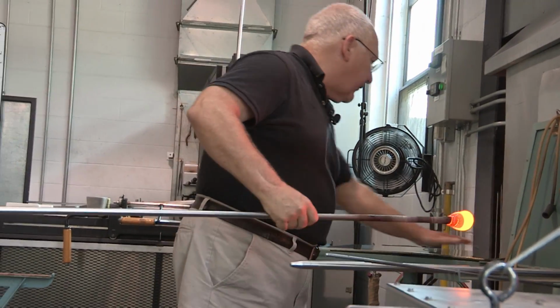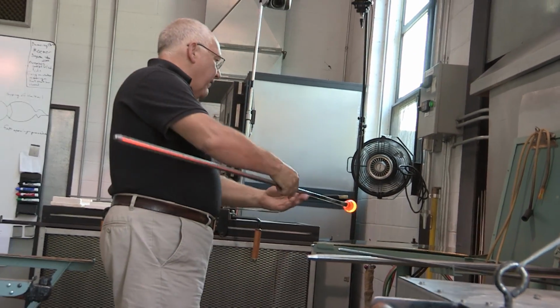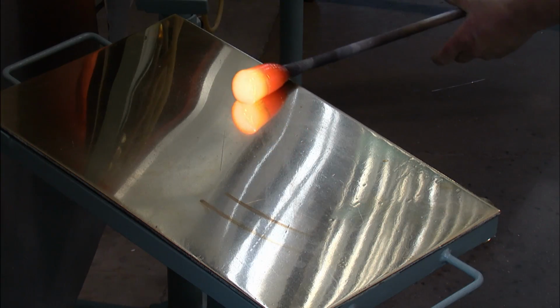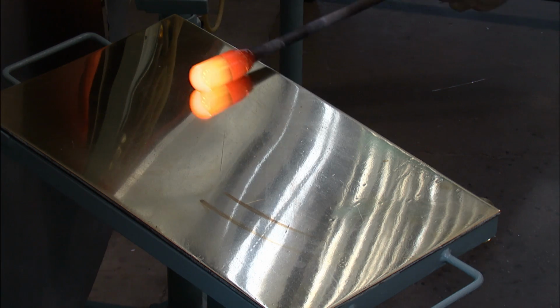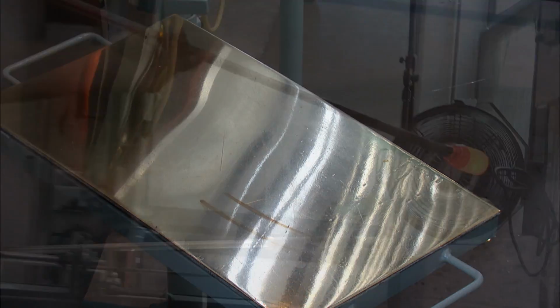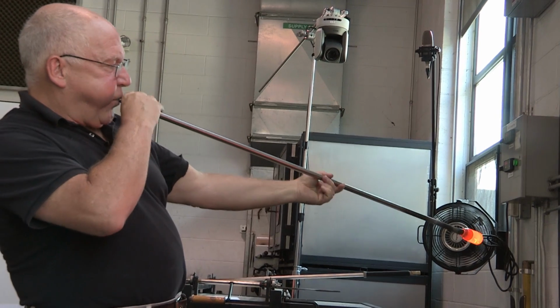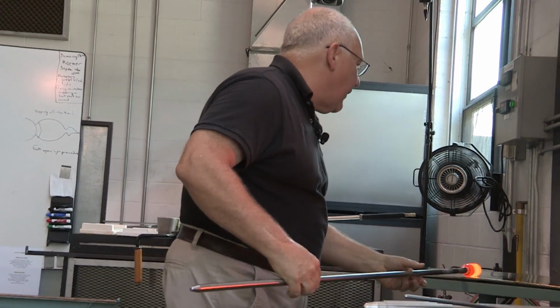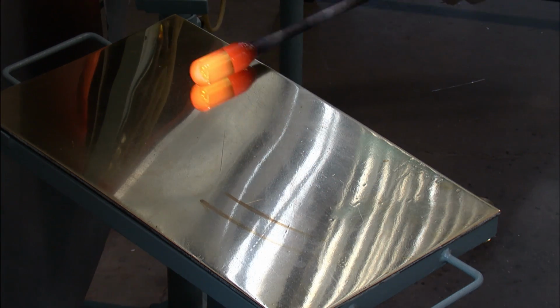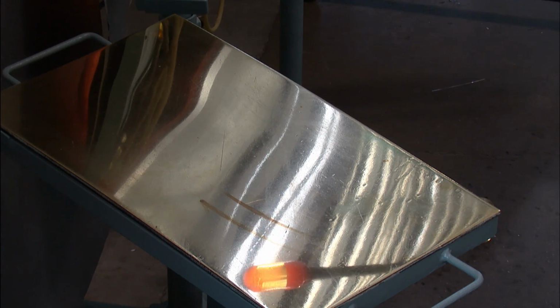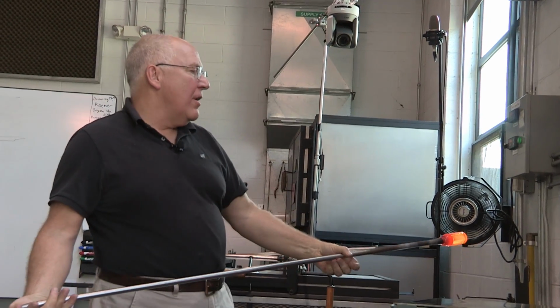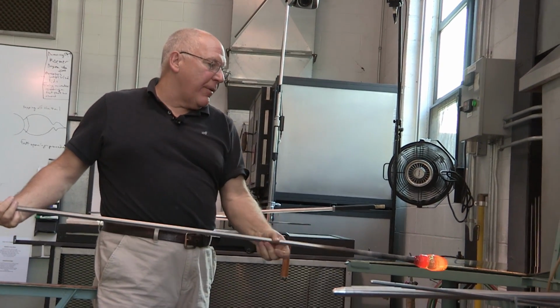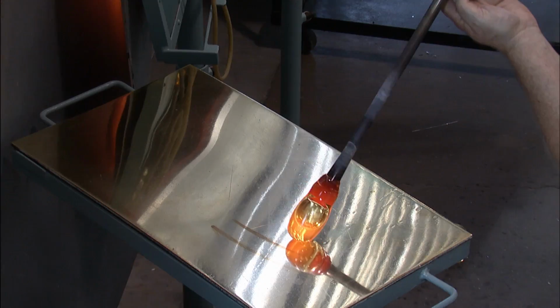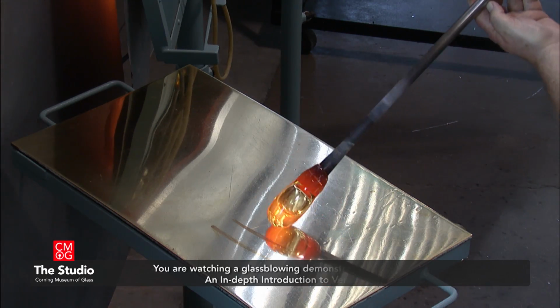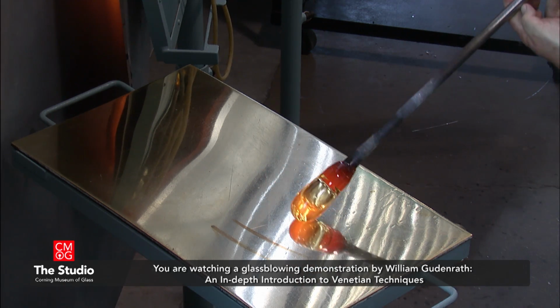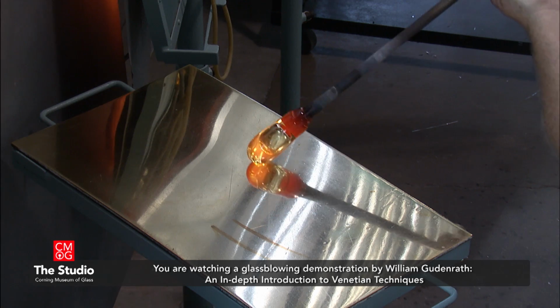I like to shape the glass in the air using gravity before I marver. I blow gently to blow the glass out of the hole in the end of the pipe. During marvering, it always gets filled up with glass. Blow that out, remarver, blow and cap at a medium pressure. And what we're doing is making the standard setup. 3/4 bubble, 1/4 solid tip. I marver the tip to make it pointed and to make it cool. This is a way of isolating a thick spot for the punty to sit on.